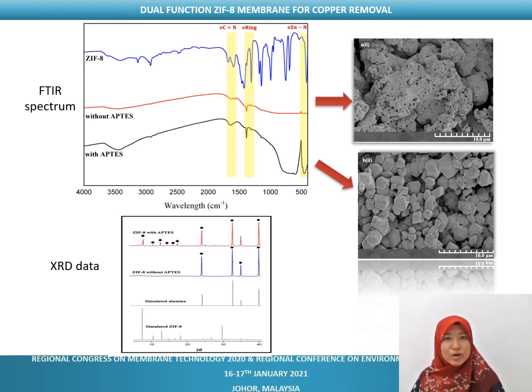Several bands was also observed in the range of 1350 to 900, associated to the presence of in-plane bending of the ring, and the bands around 750 to 690 correlated to the existence of aromatic sp2 C-H bending. And the zinc-N stretching band can be observed at wave number around 450. On the other hand, the ZIF-8 membrane prepared without APTES modification showed unclear ZIF-8 bands at the IR region.